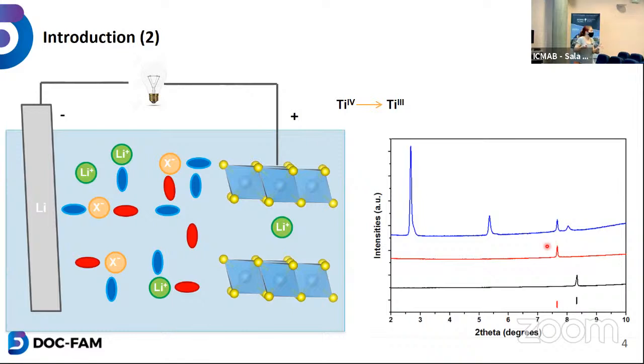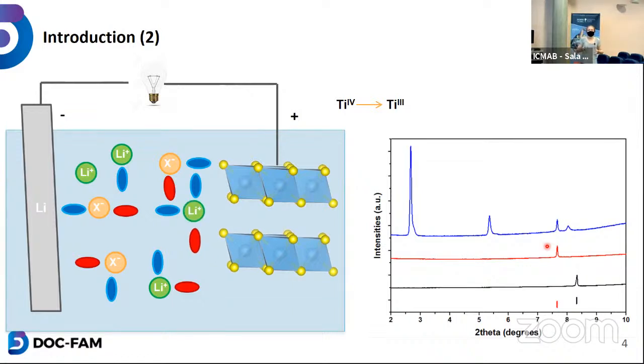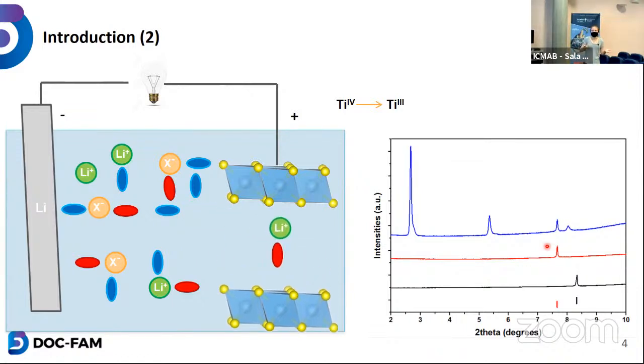However, it's not always the case, and sometimes another chemical species enters as well. In our case, it's the solvent, propylene carbonate. And on the X-ray diffraction patterns, you have three very characteristic peaks of this new phase that is much larger.